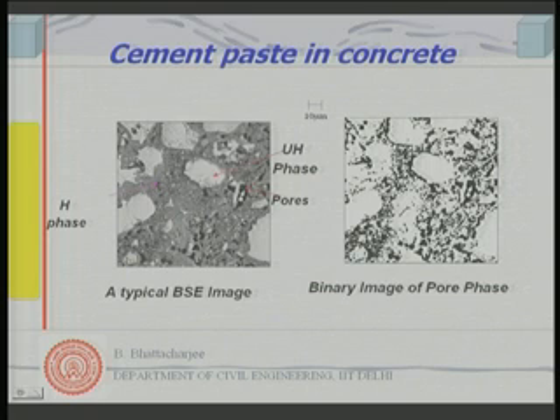If I do binary imaging, separating out by thresholding as it is called, what I do is keep all pores black and make the rest all white. So, this is the kind of pore structure you can see in a binary image. All the blacks have been left as black, and all other colors, greys and whites, have been made white. So, the unhydrated phase and the hydrated phase all look white here, and these are the pores. A typical two dimensional picture of the pores in cement paste in concrete would look like this. They are all of irregular shapes and sizes and interconnected.